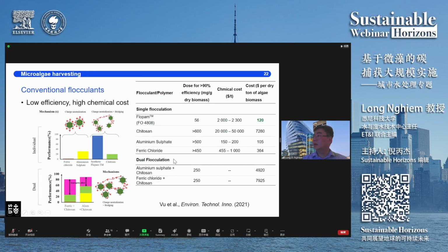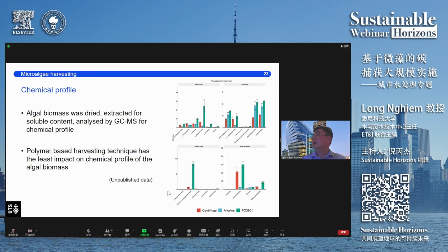it. Then we see that there is a commercial product, which is the FO 4808, that can be very effective. And if we use it, cationic polymer, we can achieve 99% harvesting, very fast recovery, and the overall cost of production is actually quite low. We work out that it's only about $120 per ton of microalgae biomass that we can harvest. But we need to look further into it because we see signs of cell damage, membrane cell damage when we do the harvesting.